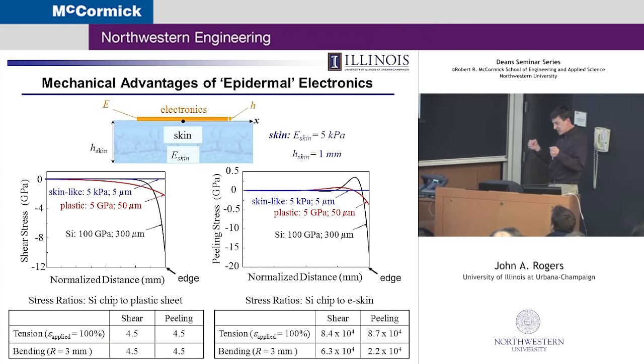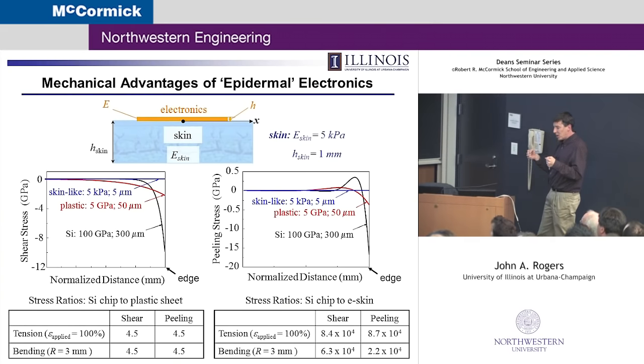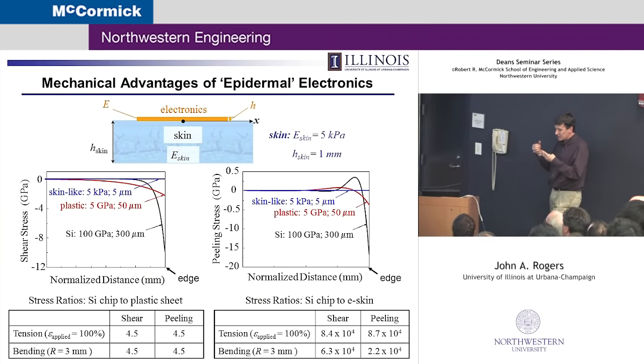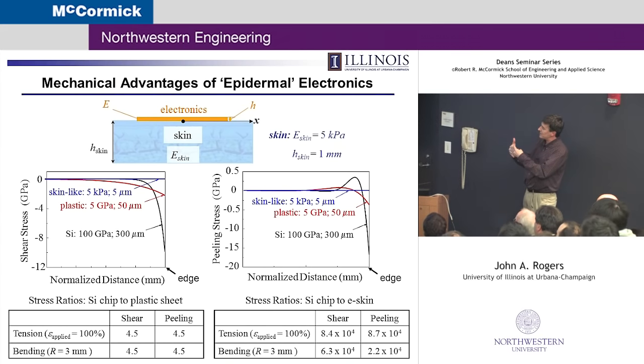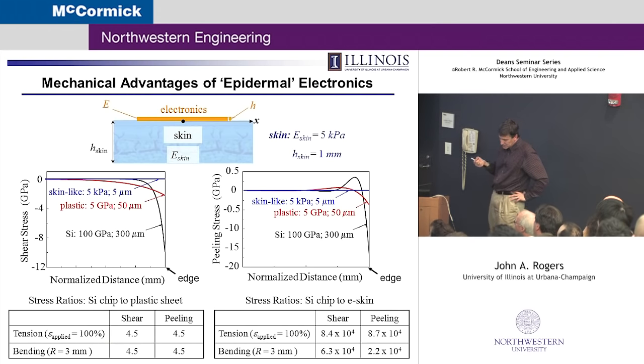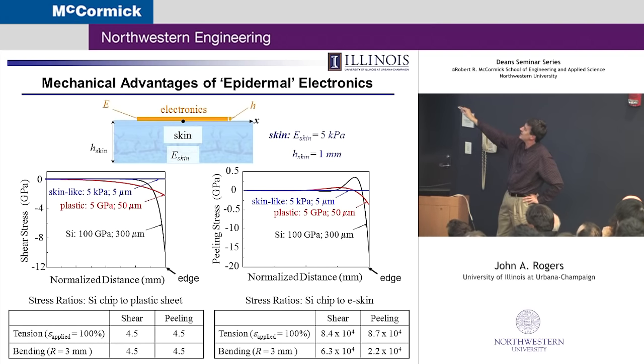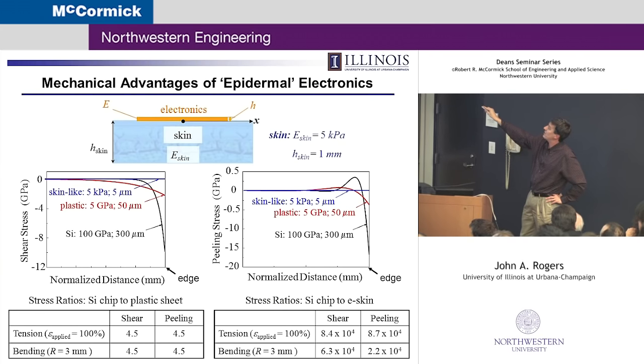So I've mentioned qualitatively a couple of reasons why low modulus is interesting. There's an intuitive sense that it's matched to the skin. That's great. It's going to be mechanically invisible. Let me just say a couple more words about interface strength, because that tends to be a key attribute that is missing from conventional technologies. How do you get robust adhesion without irritation? It turns out it's more a mechanics problem than a material science problem.